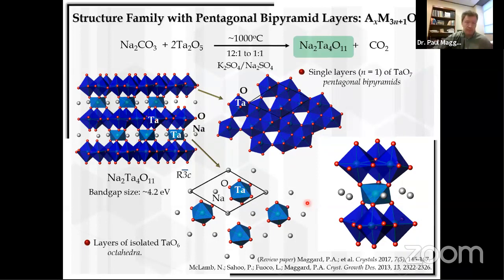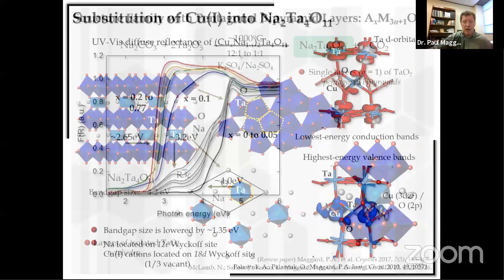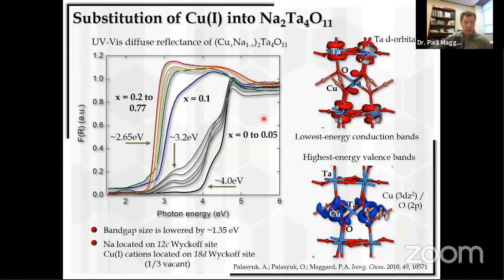of that octahedra. Okay, and the reason we chose this is that it's pseudo two-dimensional, and in this structure we can exchange out that sodium, in the chemical formula Na2Ta4O11, with all of those other main group and late transition metal cations I showed you, using our flux synthesis conditions. So we can make this material first by flux or a solid state approach, and then use what's known as a flux exchange to replace the sodium with copper, for example.